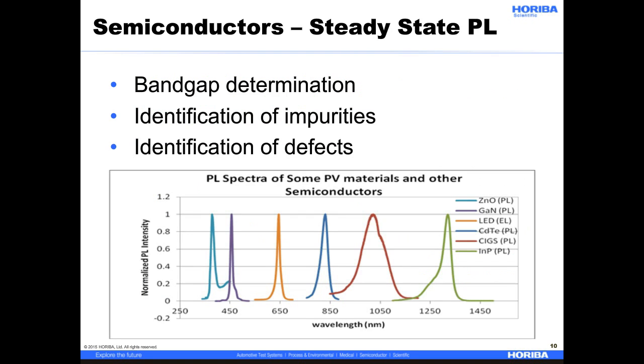By analyzing the steady-state PL spectrum, the band gap of the material under study can be determined. The following graph shows steady-state PL spectra from a variety of materials, ranging from the UV for zinc oxide to the near IR for indium phosphide. In addition to band gap determination, impurities and defects can be identified across a manufactured wafer by monitoring the PL intensity, peak wavelength, or peak width.